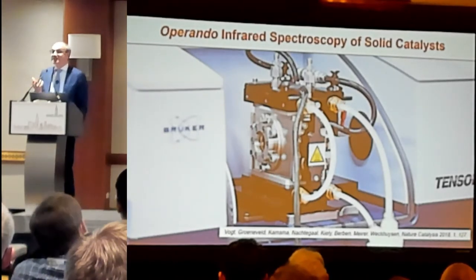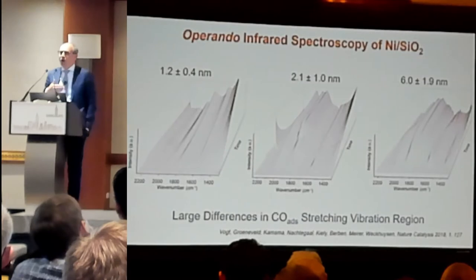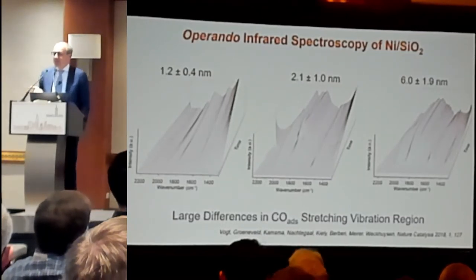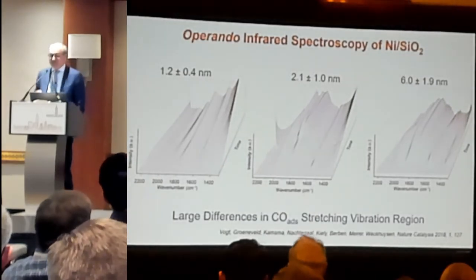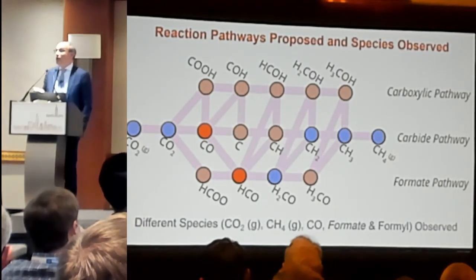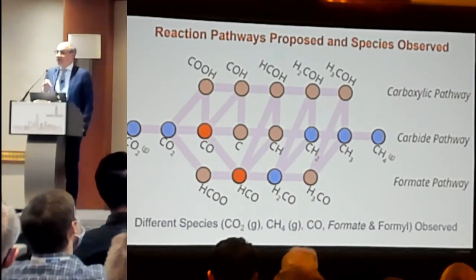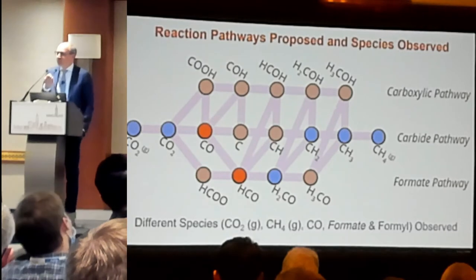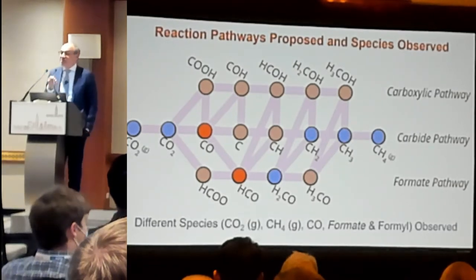We did CO2 hydrogenation in operando infrared for all metal nanoparticle sizes — 1.2, 2.1, and the in-betweens, up to 6 nm. You don't have to be a specialist in infrared to see that there are huge differences, due to the presence of different intermediates. We observe CO2 gas, methane gas, CO gas, CO adsorbed linear and bridged, formate, and formyl. The molecule from CO2 to methane follows the blue and red dots, and only the red ones we see at the surface of a very active catalyst.